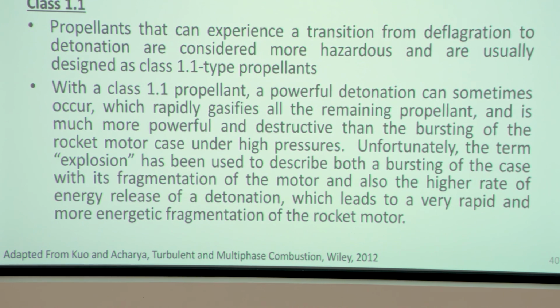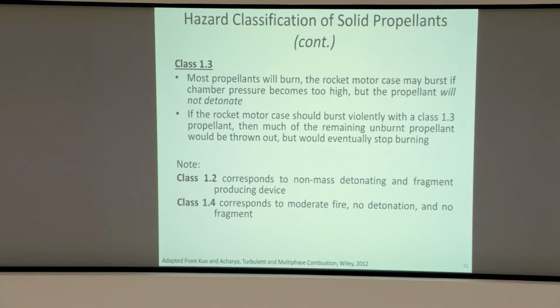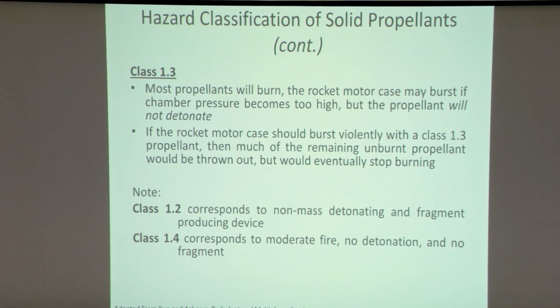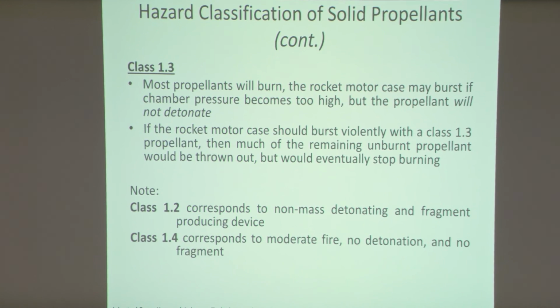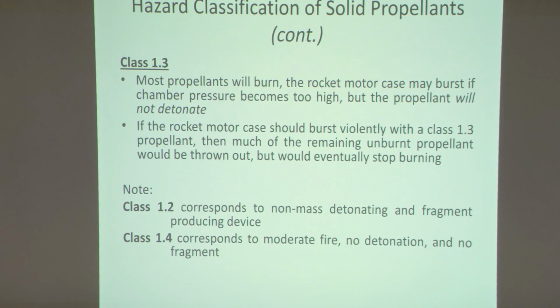One way to tell the difference between if I had a detonation or an explosion is really to look at the size of the fragments that are left over. If I find large pieces of fragments, it was an explosion. If I find that the pieces of the material are only little pieces, it detonated. Okay, in a class 1.3, most propellants will burn, and if they're in, I say, a rocket motor case, it may burst the chamber because the pressure gets high, but the propellant will not detonate. So 1.3 doesn't detonate.